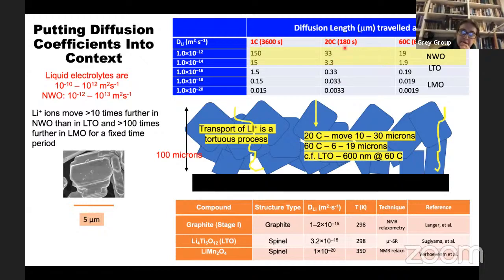charge in 20C, so 180 seconds, which I think is a reasonable criterion for fast charging, although you might argue 60C is, then you really need, if you, for example, go for 60C, then if you have 10⁻¹², then that'll get you 19 microns. And so our materials are somewhere between 10⁻¹² and 10⁻¹⁴ rather. So we can go about 10 microns in a 60-second charge. And so that's why we're able to use these large particles. And this is the comparison of the next best material, which has a diffusivity of 10⁻¹⁵. So that's why this material has to be nano-sized.